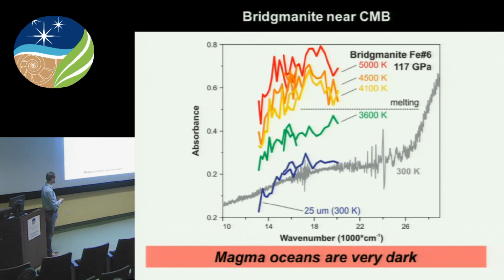This, by the way, is a Bridgmanite sample with 6% iron at 117 GPa, shot up to temperatures of about 5,000 Kelvin. If we now extract absorption spectra from here and compare them to the absorption spectrum of the same sample taken with a conventional absorption system, which is this gray spectrum, you can see that at high temperature you get an absorption spectrum that is very, very different from what you have at room temperature. Then as the sample cools off to approximately 4,000 Kelvin, this absorbance changes, but maybe not that drastically. The general shape remains the same.